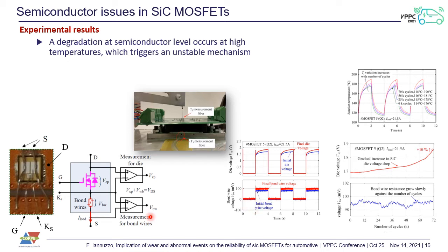The bond wire voltage drop was also increased, but we were able to discriminate what the difference was between the semiconductor alone and the bond wire alone. And you can see the results in this picture, where the semiconductor voltage drop is the red one and the bond wire voltage drop is the blue one. There is a slight increase in the bond wire, some ups and downs, but obviously the semiconductor voltage shows a definite and, I would say, very remarkable increase, around 10%, as pointed out in this picture.